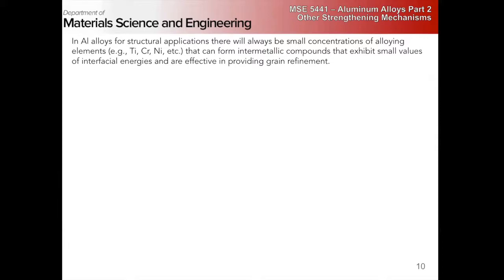So really the pinning effect is just to keep the grain boundaries from growing. When you get very fine grains, you get increased ductility because you delocalize your slip, right?